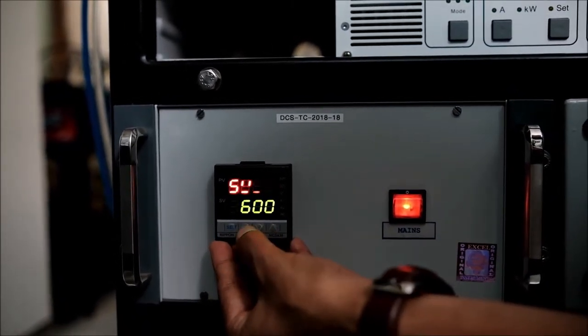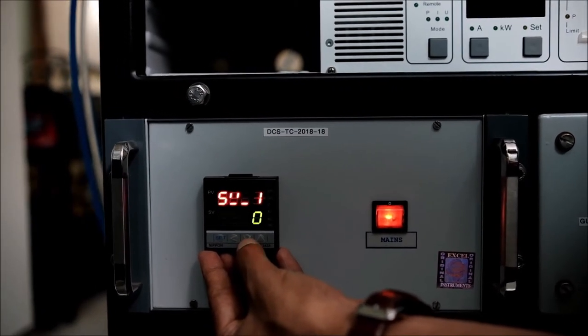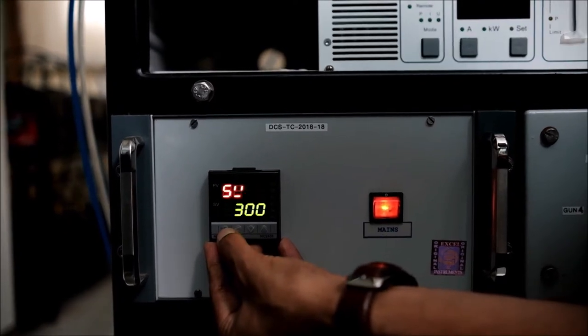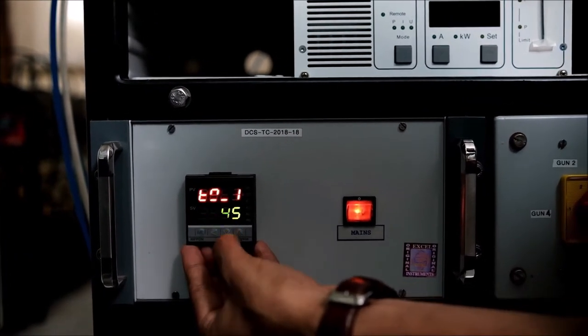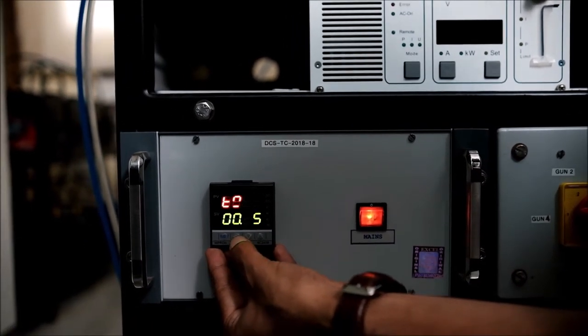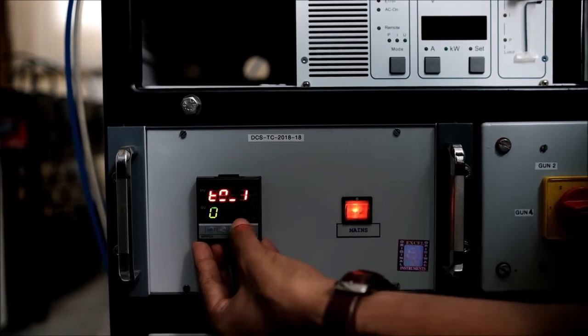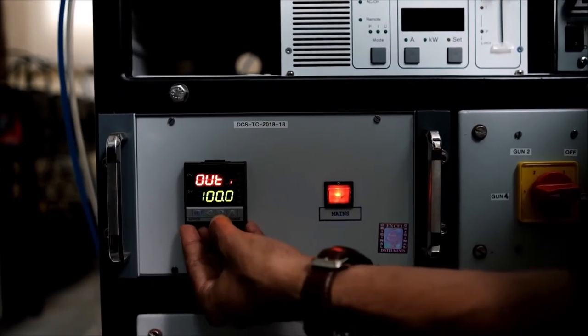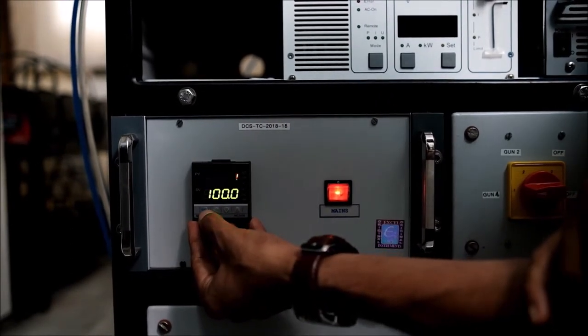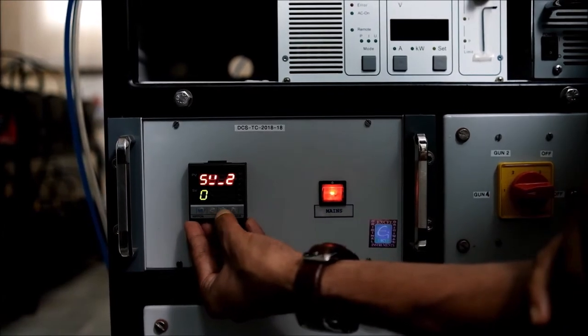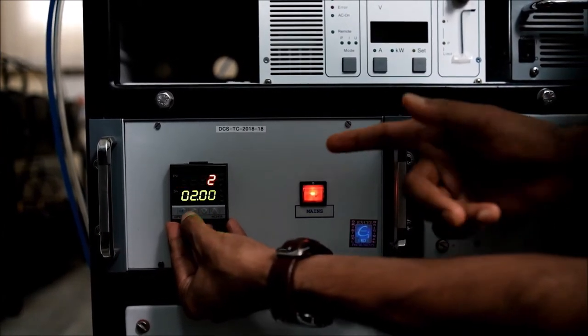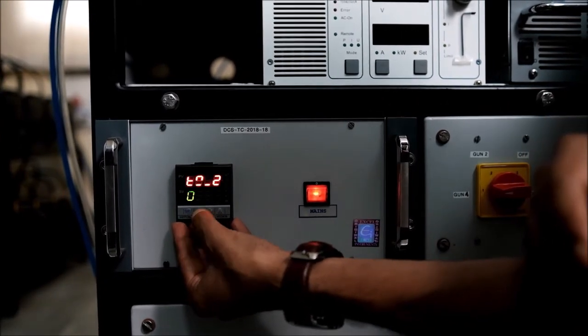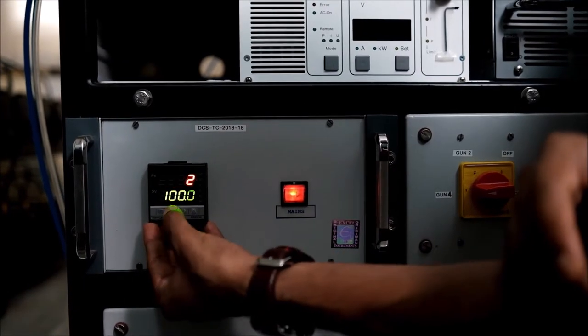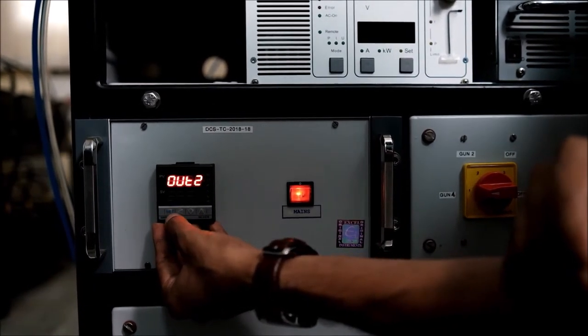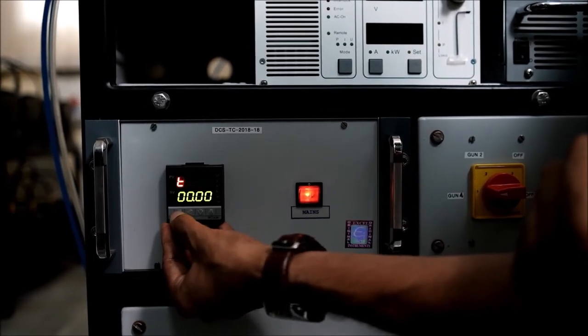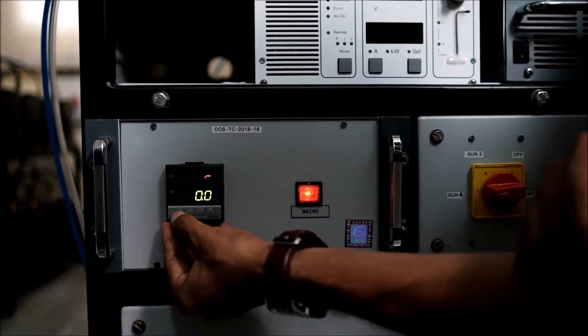So I will do the setting. This is the first segment, so there I will set 300. So now it is 300 degrees Celsius. I want to reach 300 degrees Celsius in, let's say, around 15 minutes. So I'll set it so in 15 minutes it will reach 300 degrees Celsius. This is the output power percentage. I can keep it at 100%, and then I want to stay at 300 degrees Celsius for an hour maybe. So it will stay for 1 hour, and output will be 100%, and all other parameters I will keep at 0. It is already 0, so no issue. So all other points are kept at 0.